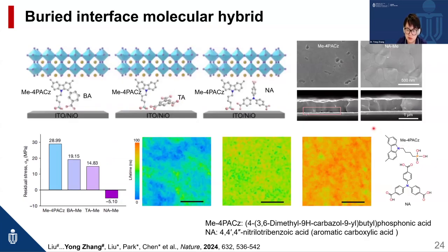So we introduced a buried interface molecular hybrid method by mixing Me4PACz with nitrilotribenzoic acid, NA, to improve the wettability and distribution on the ITO substrate, and also passivate the perovskite buried interface.